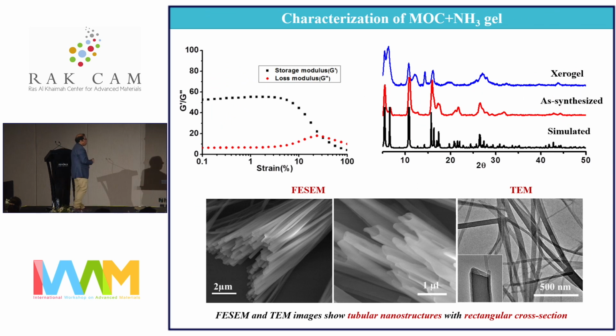So then, through rheology measurements, along with FESEM and TEM, we see this beautiful nano-tubular morphology. In the aerogel, the three-dimensional architecture remains intact at the micron scale, with diameters of around 80 to 100 nanometers and thickness of 9 to 15 nanometers. Around 7 to 8 gallium MOCs are assembled to form this structure.